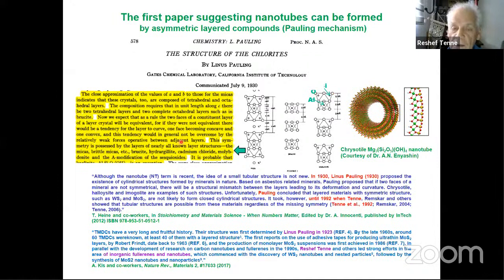Consequently, in the first paragraph of the paper, he predicted that these structures will not be stable as planar structures and will form tubular structures, in our concept, which did not exist, of course, at that time. There was no electron microscopy to verify nanotubes, but yet he predicted via his X-ray studies that these materials are not stable in the planar form and will form folded structures. It took another 20 years to find these nanotubes, in the 1950s, when electron microscopy was of high enough resolution to observe such nanotubes. These first nanotubes were reported.